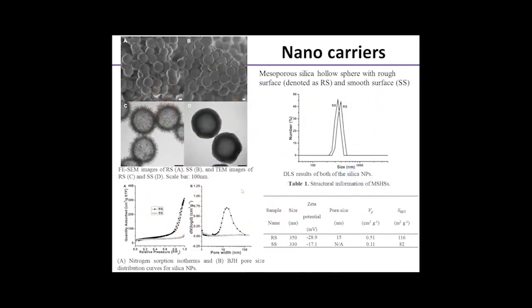So here are some of our results. Mesoporous hollow spheres with a rough surface, denoted as RS, are shown in this slide. The dynamic light scattering result showed good dispersity of this nanoparticle. The shell of the RS was covered with nano-sized silica spikes to form the rough surface morphology, mimicking the surface topology of pollen grains. The nitrogen adsorption results shown here indicate that the RS possess 15 nanometer mesopores, which come from the void space